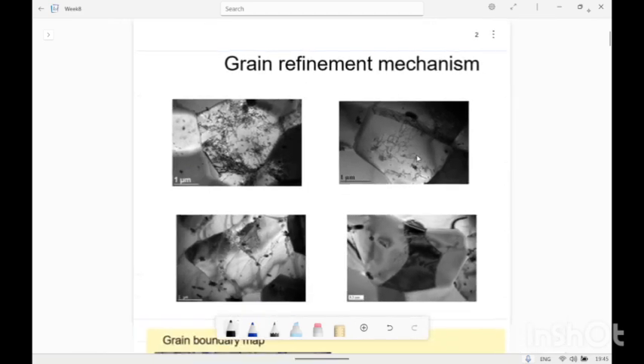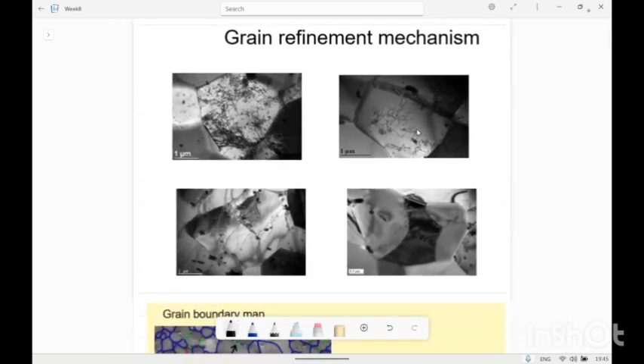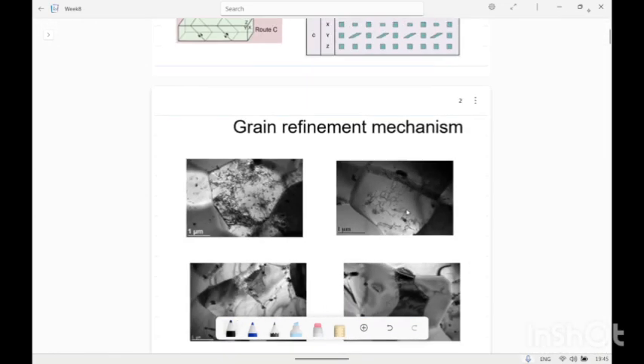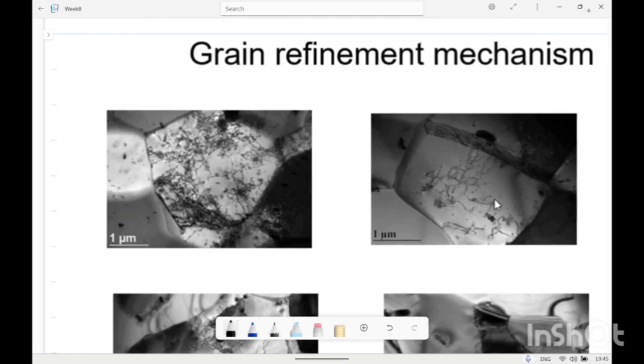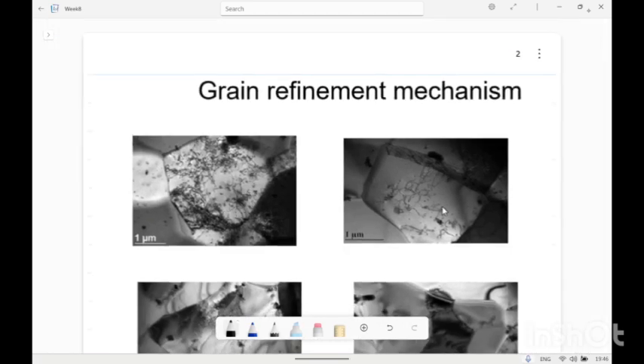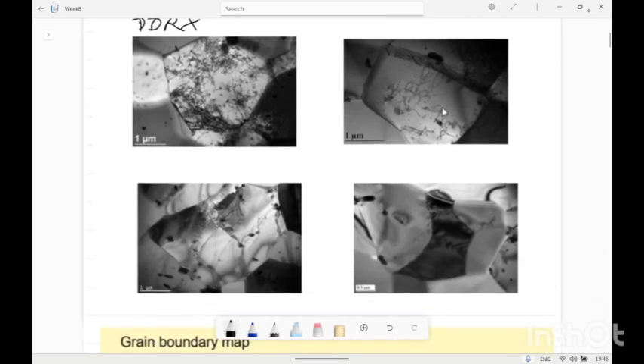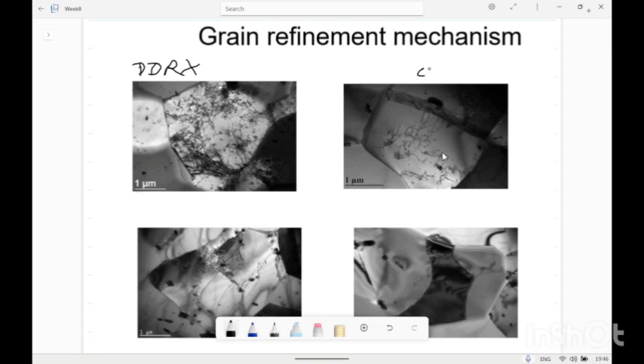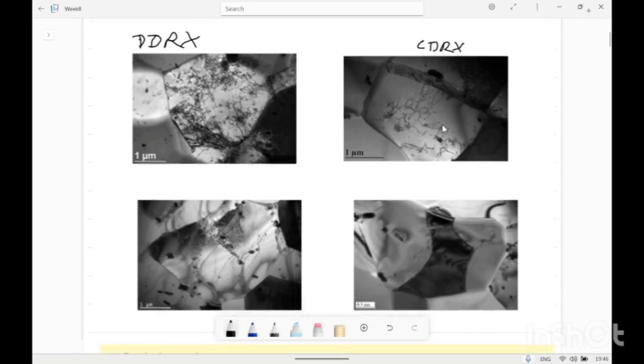So in these pictures, grain refinement mechanisms are shown. In the first picture, we can see that the dislocation density is very high in one grain, while the neighboring grains do not have any visible dislocations. So a strain gradient exists in this material, and this is a case of discontinuous dynamic recrystallization process. While the second can be continuous dynamic recrystallization, because there is no accumulation of dislocations in one grain.